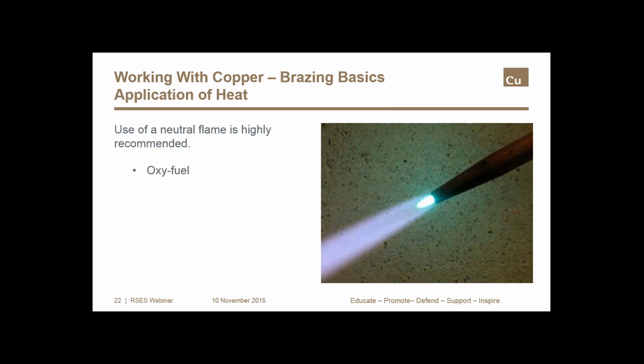We want to apply heat to the parts to be joined with an oxy-fuel or an air-fuel torch. The photo on this slide shows an oxy-fuel torch. You want to adjust the oxygen flow to a neutral flame. A neutral flame has a minimal glow near the nozzle, as the photo shows. The Copper Development Association recommends avoiding a carburizing flame because of the excessive amounts of carbon that this flame introduces into the joint.